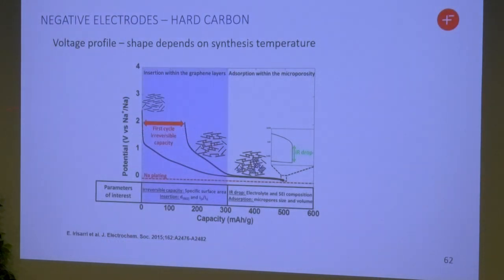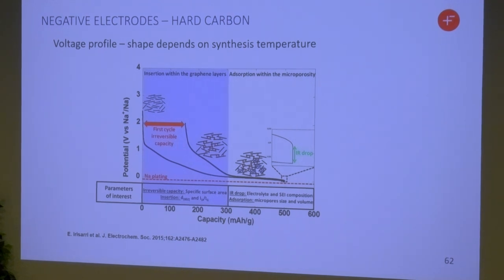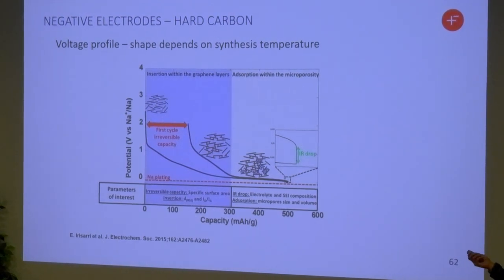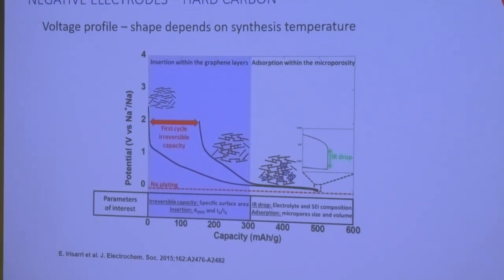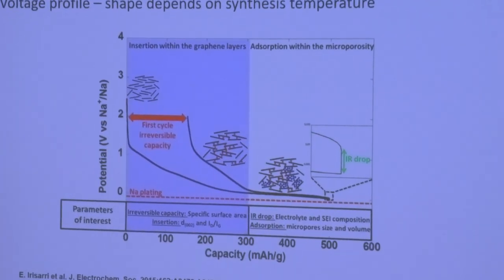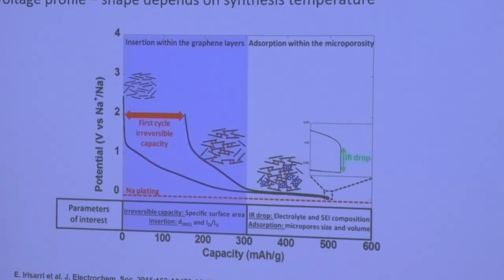Quick bit on the negative electrode. This is hard carbon. It's a mixture of sort of graphitic bits and pores, and as you insert sodium, in the first sloping region you're inserting sodium in between the graphitic bits, and then it goes into the galleries in the structure along this plateau there. It's quite successful. It does have issues.